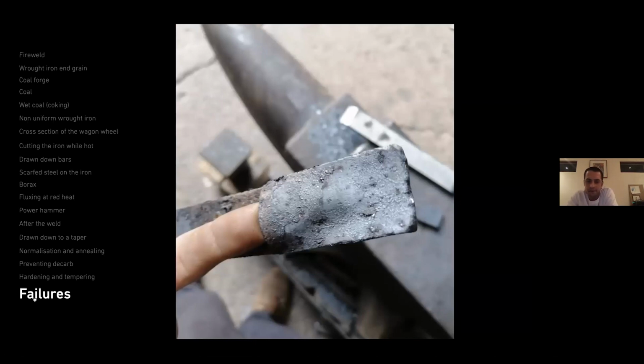In learning to weld, and even while welding, once one has a known process, there are failures. Generally failures come down to either not being able to bring the piece up to welding temperature, a hot enough temperature, or having some dirt in there, or just letting it cool down too much before getting it to the anvil and hammering it. Too much lag between the fire and the anvil.